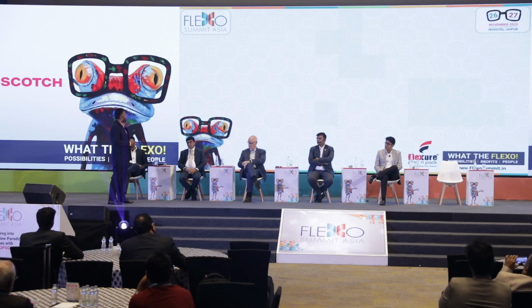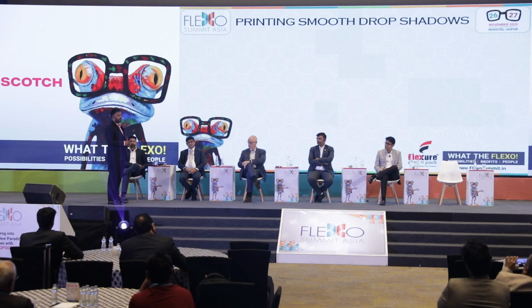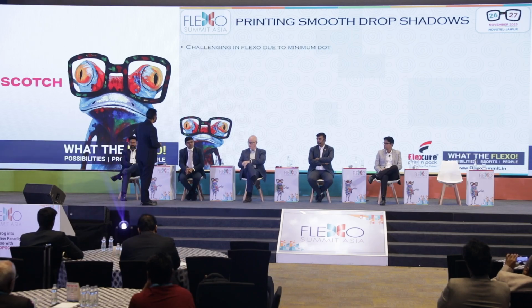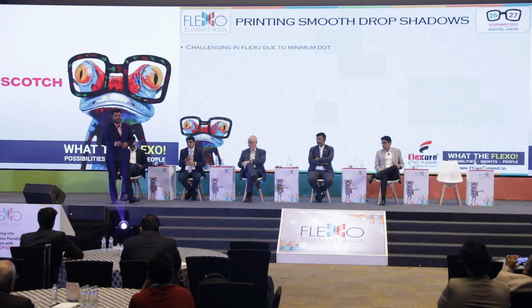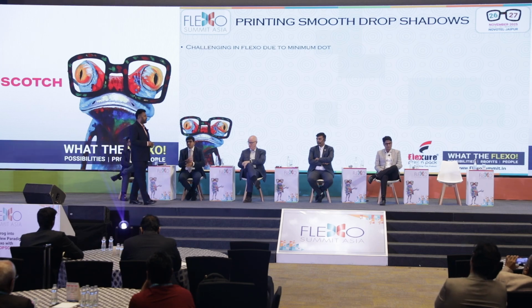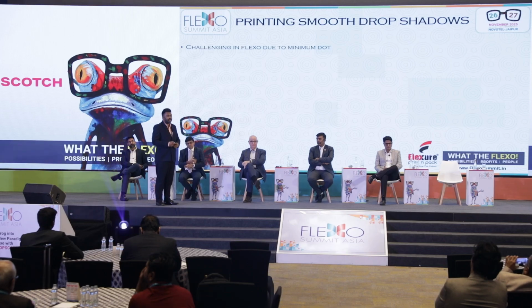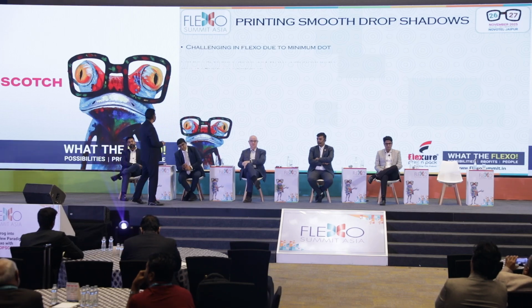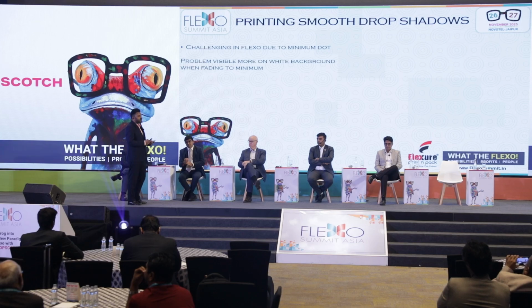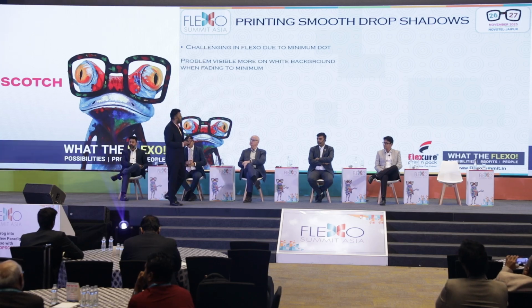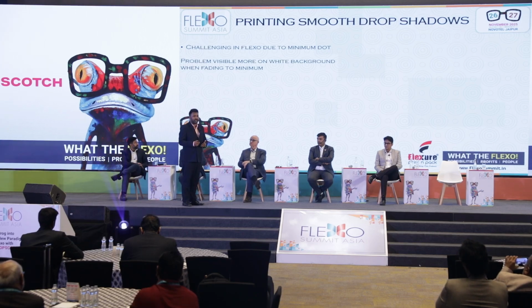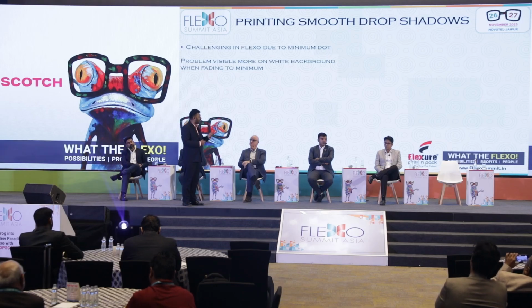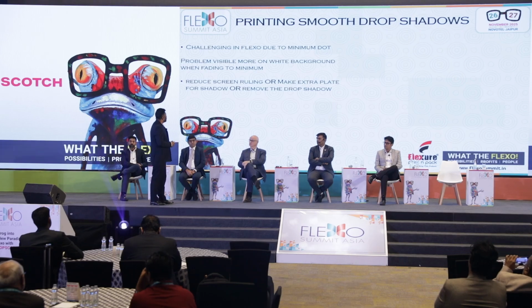So the next challenge for Flexo is to print smooth drop shadows. Drop shadows are a big challenge for Flexo. It is challenging due to the minimum dot a press can hold onto the substrate. Dots smaller than the minimum dot tend to drop out, or they gain excessively due to the impression pressure. This problem is more visible on the white background because the contrast value is very high. The substrate is white and the shadows are black, so the contrast value is very high, so it looks very dirty over there.